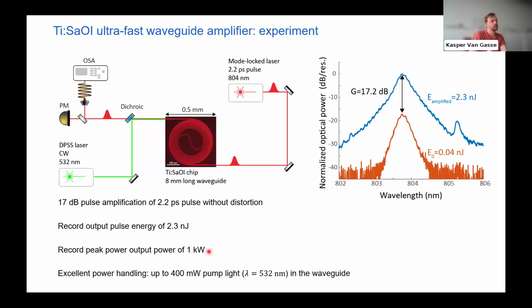And on top of that, from this experiment, we learned that the titanium sapphire waveguides really have excellent power handling. We could operate this for hours or days on end without any degradation of the performance. And this while we were at some point pumping about 0.5 watt of green light into this waveguide for hours on end without any degradation of the waveguide. So that's really very encouraging for high performance lasing on chip.